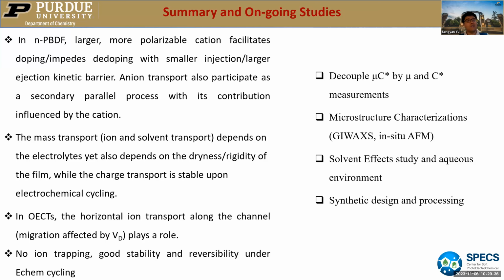But the good thing is that the charge transport is barely affected by the electrochemical cycling. And in OECT, the performance can be a little different because the migration of the ion or cation along the channel can also play a role. So if we want to use this as a polymer conductor to replace ITO, it has a very promising future because we didn't see any kind of untrapping. It shows very good stability and reversibility in the electrochemical cycle. So there are a few ongoing studies I'm going to carry on with this polymer.